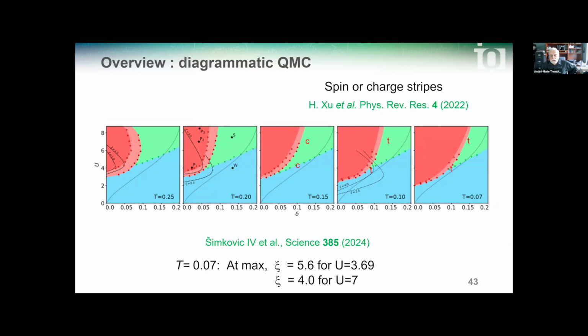Note that starting from the left plot, you see that the lines of constant spin correlation length are curved. At constant doping, it means that the spin correlation length increases, then decreases as a function of interaction, as one moves from U less than the Mott transition at that filling to values of U larger than those of the Mott transition at that filling. The bottom line here shows that at the compressibility maximum of the TPSC this time, the spin correlation length is larger for smaller U.